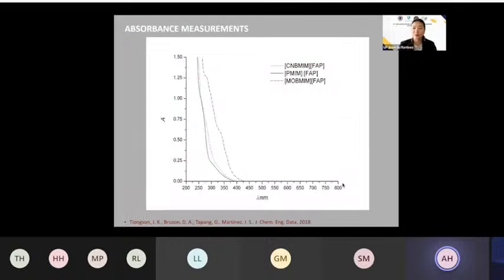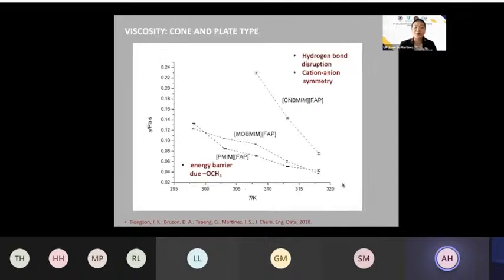And then, of course, to determine that our ionic liquids are pure and there are no organic compounds dissolved in them, we also do absorbance measurements. And as you can see here, our ionic liquids are really quite colorless. And then, of course, we look at the viscosity of the ionic liquids. We know that as you infuse gases into your ionic liquids, their viscosity will increase. So it's always good to start with compounds with low viscosity.